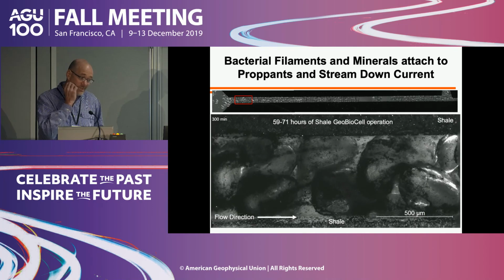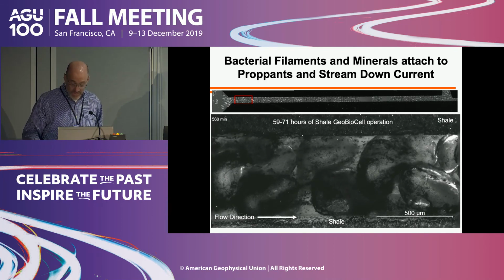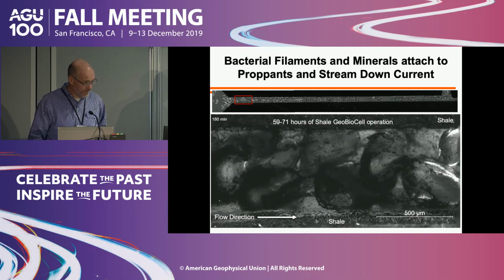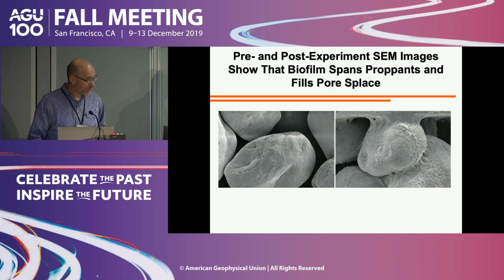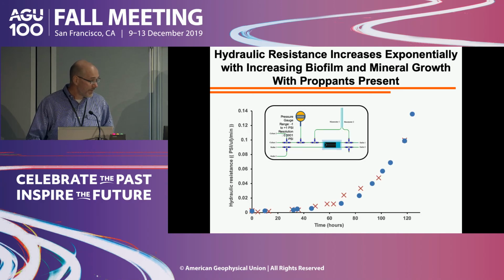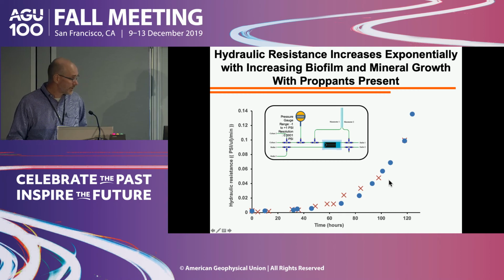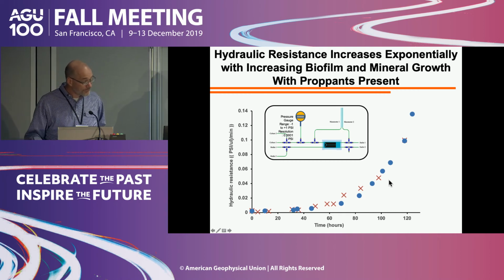When you have proppants there, there's a lot more of this biomass in the channel, and there we start to see some pressure increase in the system. This SEM image shows before and after what these grains look like and how you get this biomass. Here it's collapsed because it's dehydrated, of course. If we look at the pressure drop, we get this characteristic behavior where, when the proppants are in the system, at some point we start to get an exponential increase in the hydraulic resistance. That's something of concern, certainly, or it could be good if it's a cap rock.